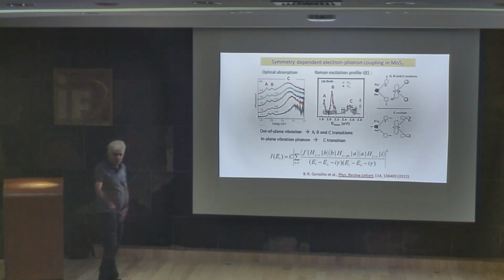And that's one question that Laura was asking me, because how can we get information about the width? It depends a lot on the environment, not only the width, but even the position. Okay, then the conclusion is that we could observe that some phonons couple with excitons and another one does not couple. That's what we call the symmetry-dependent electron-phonon coupling.